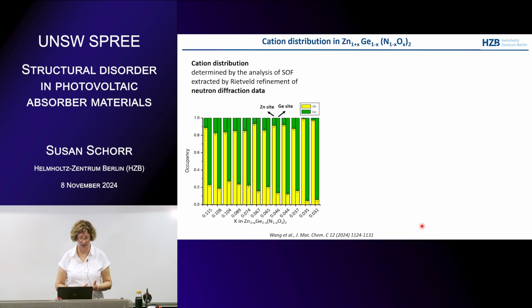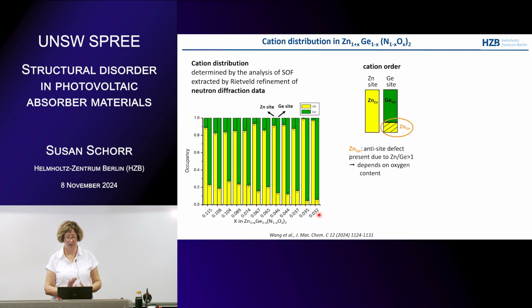Now, where are the cations? So we have two sites, as I said before, the zinc site and the germanium site. And this is again the site occupancy, so one is full. Two columns always belong to one sample. And this is for different oxygen contents. So this is a high oxygen content and this is a lower oxygen content. And this figure we would expect if we had full cation order. So the zinc site would be occupied by zinc only, and the germanium site by all of the germanium and a little bit of zinc because of the oxygen. We have a zinc to germanium ratio which is always larger than 1.